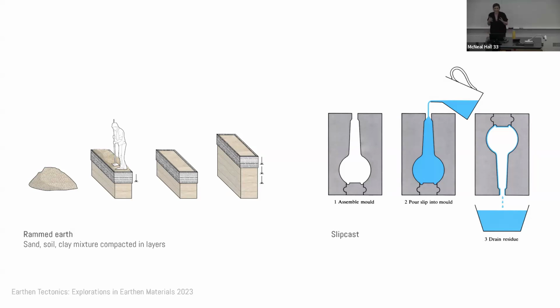So slip casting, for those of you who might not be familiar, is a ceramic reproductive process where you take really thin ceramic slip and you pour it into a plaster mold that absorbs the water, leaving a solid clay layer that hardens into a final shape. So it's very thin and delicate. And then rammed earth compacts damp subsoil as a stabilizer in layers between formwork that create dense monolithic walls.